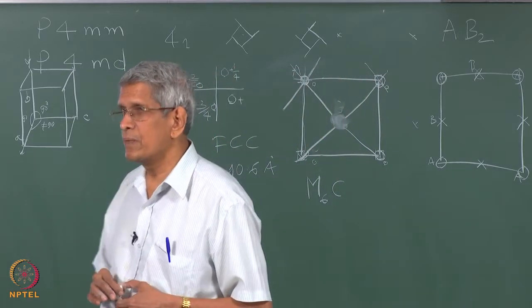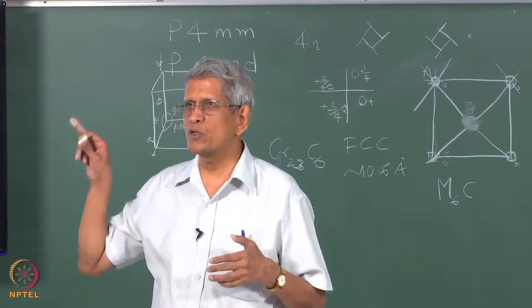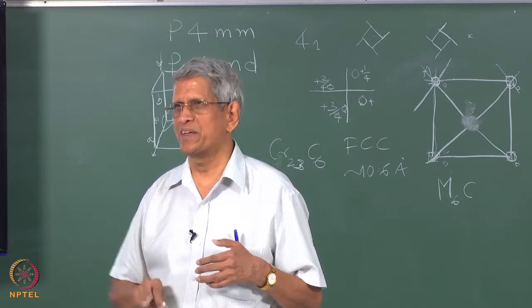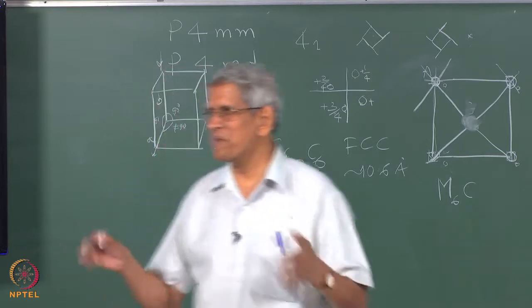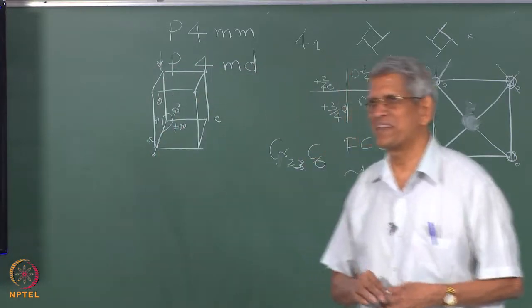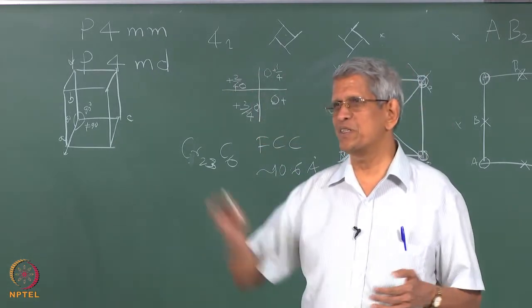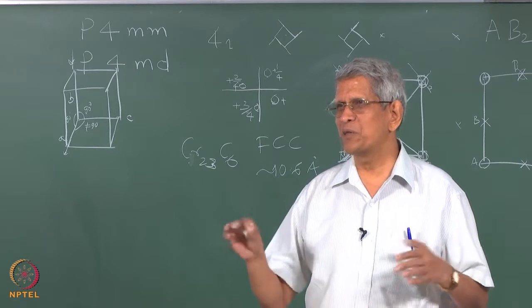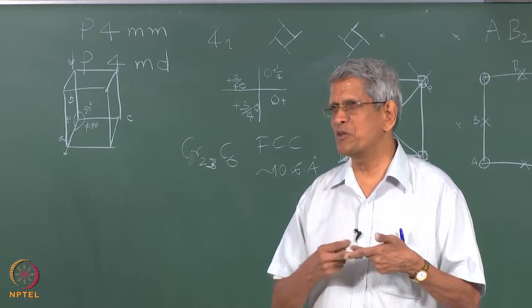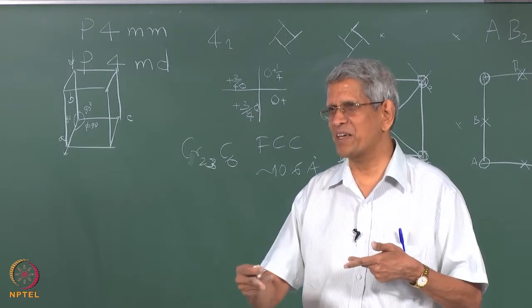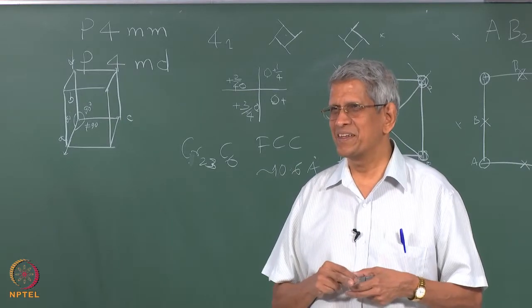What if, like shearing, by deformation it can bypass transformation? When you do deform, you are introducing a defect into it. That's essentially what it is. So that's what I meant, that unless you introduce a defect, you cannot do that. If a perfect dislocation is shearing the material, you will not be able to generate HCP in FCC. Only if the dislocation splits into partials, which means we have generated a stacking fault, essentially a defect in the stacking sequence, then it's possible.